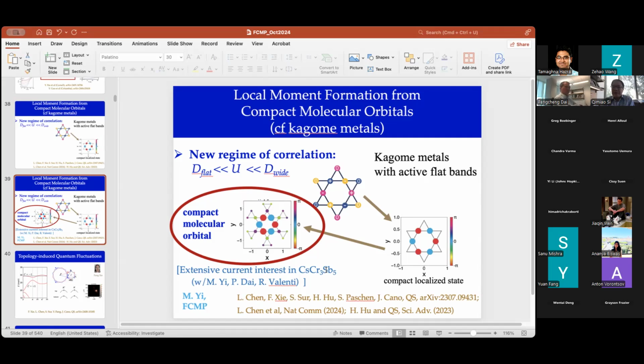This is the point that I want to show. The experiments are beautiful. They are published. They are free. Some of the effects have been seen 15 years ago, but the most recent on the transport are only 3 or 4 years ago. But they are there, and they were extremely robust. Okay, I agree with you. Putting the other Kagome metals being studied, this is an example. There's a number of others, and the cobaltates and etc. The advantage of the cobaltates is we know they are strongly correlated. And as we have effects which occur at low temperature, well below 30 K, we know that we have a very narrow band.